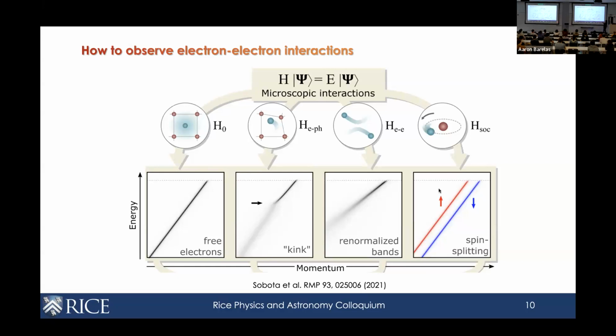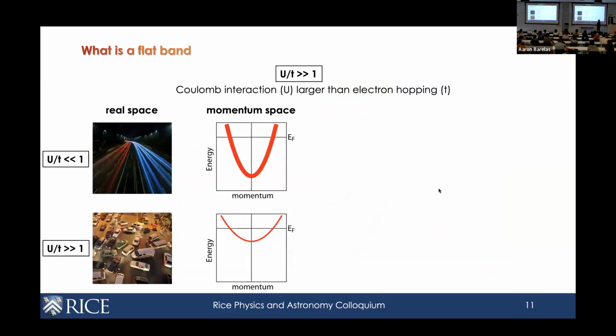We're also sensitive to electron-electron interactions, which are shown here. If the electrons are interacting with each other, they will slow down because they're talking to other electrons. The effect is that the slowing down is also produced in a renormalized slope, so the slope is also smaller. We can also gain spin-resolved information. If the electrons carry a certain spin texture, we can also see that from our ARPES measurements, right? So you can see there's a lot of information captured in the single particle spectral function we can measure with our tool.